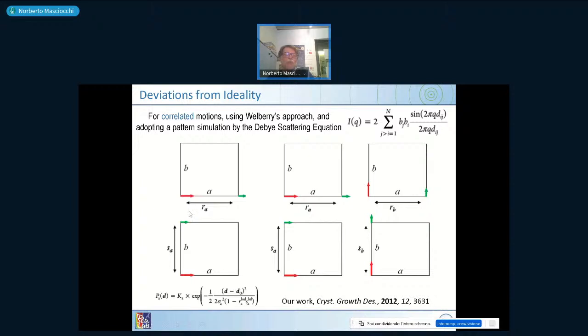Of course, if I pull in one direction, there could also be an influence of a neighboring row. And if I pull this one in this direction, you may have a transversal correlation in this sense. So if I pull one thing in one direction, I may have a consequence on the next neighbors along the direction, which is longitudinal, or a consequence in the transversal. Things are more complicated if you have a two-dimensional paracrystalline system, because if I pull horizontally, then I may have some shift here horizontally and some shift also on the upper layer. But if I pull vertically, then I may have some longitudinal shift for the same direction also here.